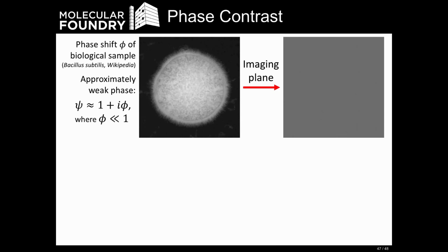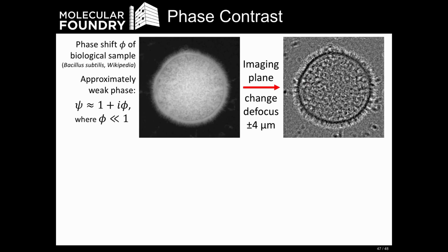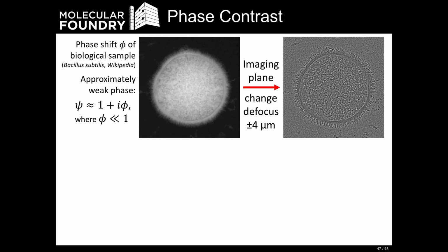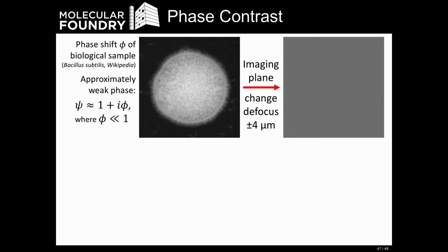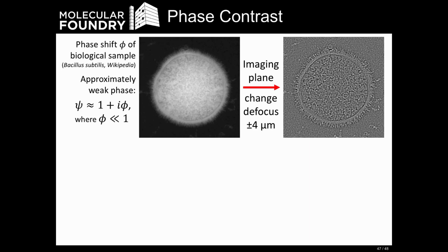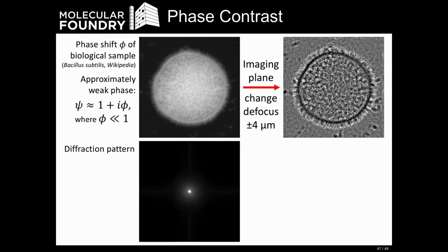contrast, and that's because you need to either introduce aberrations or somehow modulate the phase to transform some of the phase signal into intensity signal. That's because for a weak phase object, at least, the phase is not observable quantum mechanically, only the intensity of the electron wave is. So if I introduce some kind of aberration, the typical one is defocus. Here I'm flipping between plus and minus 4 micrometers defocus. The invisible phase signal becomes visible, and we can see a lot of the fine structure of the sample.